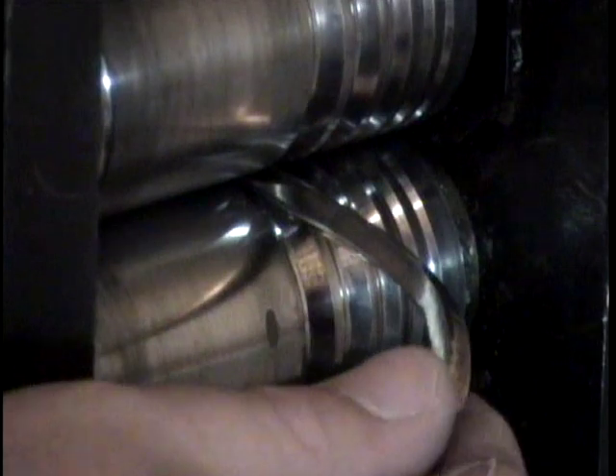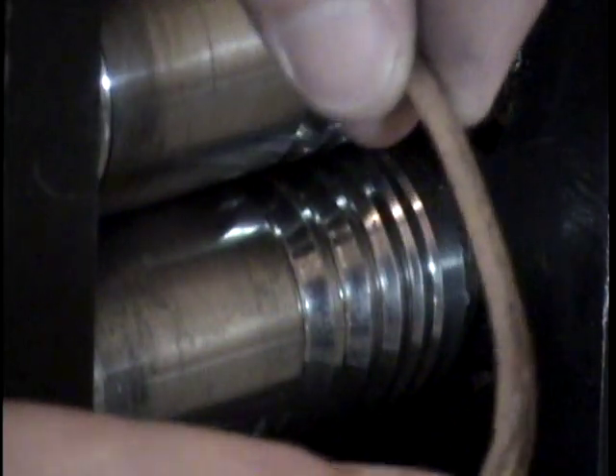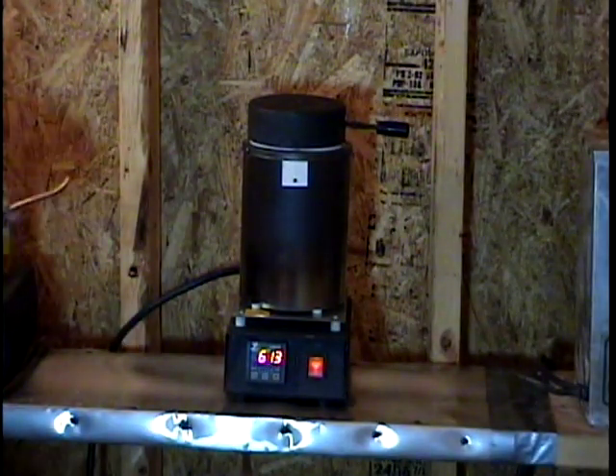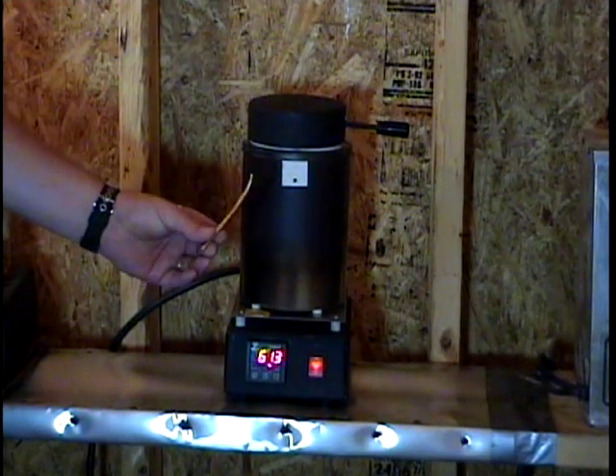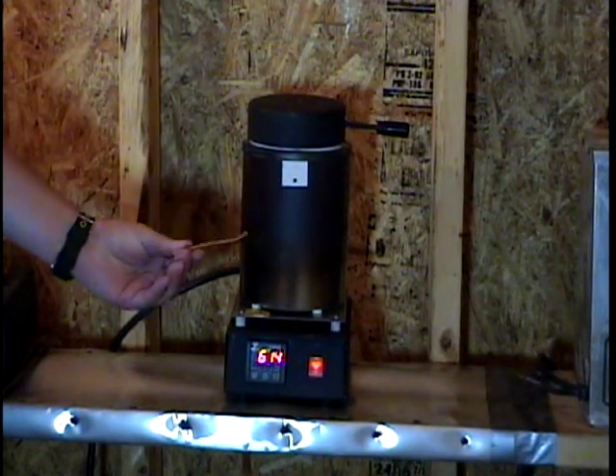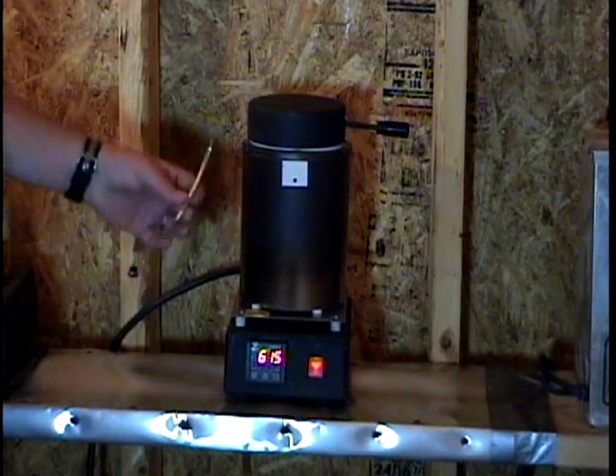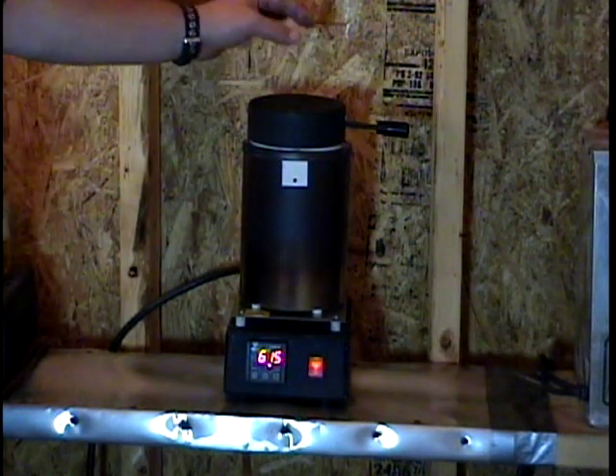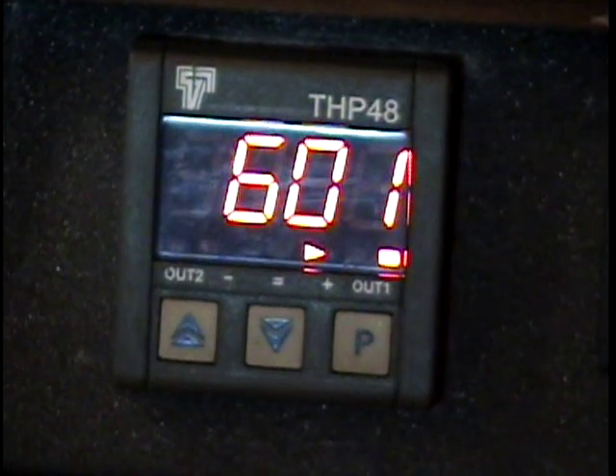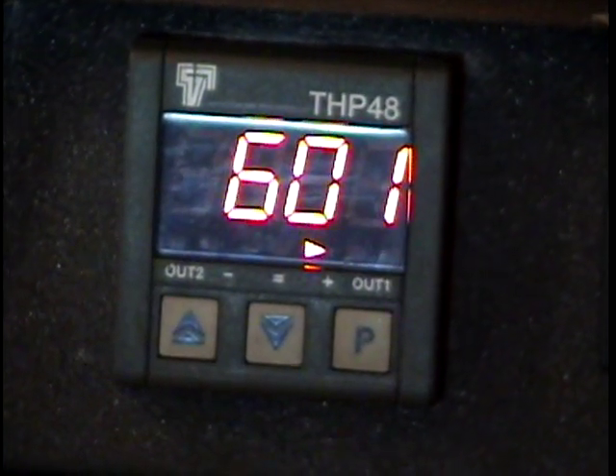Every time a piece of metal is bent, beaten, milled, or drawn, that kinetic energy is stored in the metal as potential energy, or stress, and must be annealed or heat-treated regularly throughout the process to relieve the stress and keep the metal from breaking. An induction melter works well for annealing yellow gold because of its ability to efficiently maintain a high temperature. We'll anneal this piece at about 600 degrees Celsius for about half an hour.